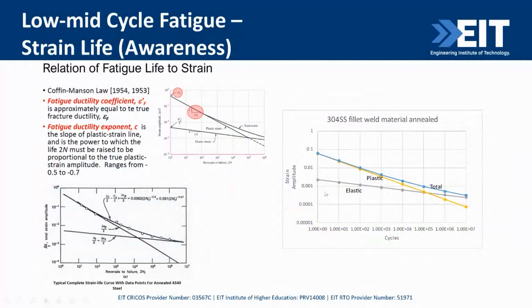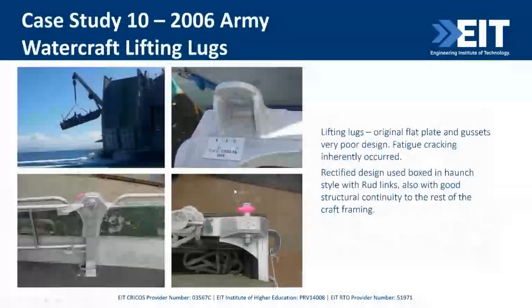So just for awareness, stress life we've been talking about, and stress life is the fatigue I've done, but strain life is low cycle, high strain, and strain life looks at elastic strain and plastic strain and then total strain, depending on your cycles, and its parent material, and be aware of strain life. There are plenty of codes, obviously, that do the stress life as well as strain life. This is a strain life, low cycle situation of the lifting lugs of this army barge, army watercraft, sorry.